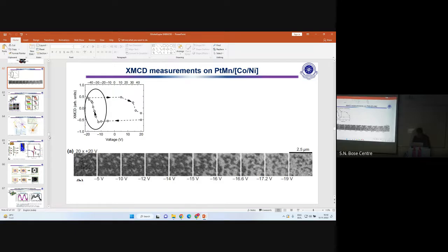And what is the lower one? That's XMCD, at different spatial positions and different voltages, like 5, 10, minus 5. Here you first saturate the magnetization at one point. You apply different currents and then take snapshots of the magnetization. You basically trace out the transport signal in an optical way so that we can see what is actually happening inside these magnetic domains. The white region is ferromagnet. The white and black correspond to ferromagnets with opposite magnetization directions.